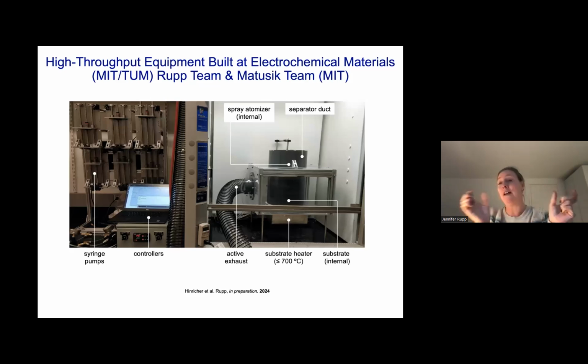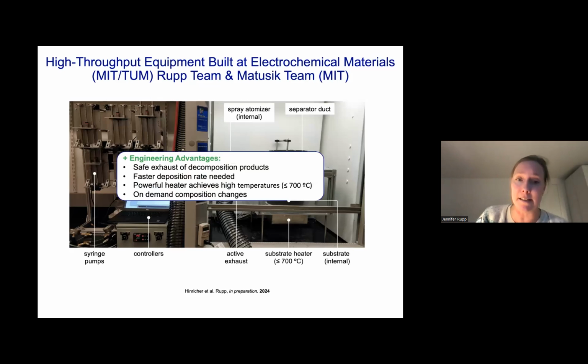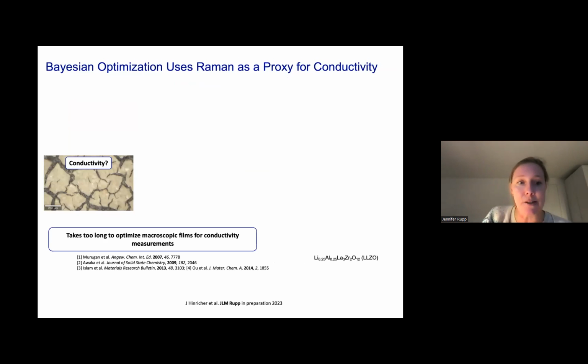And we can on the fly mix different cations together. So it's a little bit like, when you think about it, some science fiction where you just mix the elements that you want to have in. And the theoreticians love doing that in DFT, but we do that here in a real-life experiment. So we can just define different precursor lines, there are many attached to it, and mingle in the organic solvent different concentrations of the salt, and then we can deposit the films at certain temperatures and conditions, take them out and then analyze them. And it's, I think, our own construction that we made here, and I think it's quite powerful.